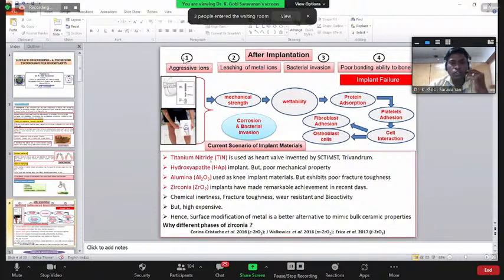Okay, in zirconium oxide itself, three phases are there. In pure zirconia, it exists in the monoclinic form. If you add a small amount of yttrium, around 4 mole percentage of yttrium into that zirconia, it will become tetragonal. If we add 10 mole percentage of yttrium oxide into the zirconium oxide, then we can get the cubic nature